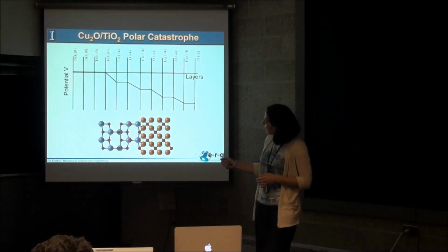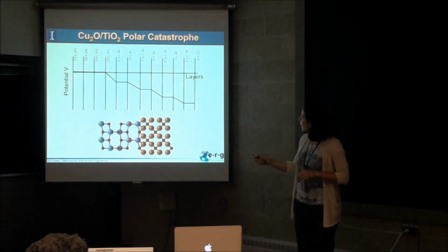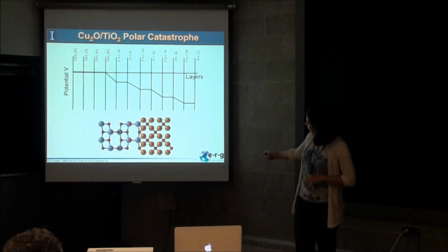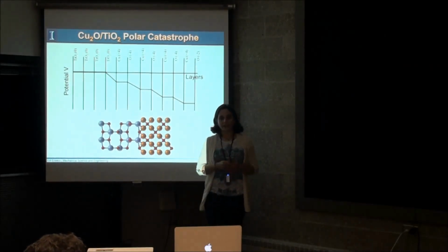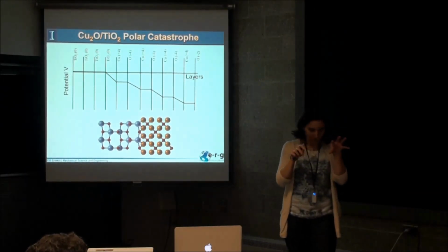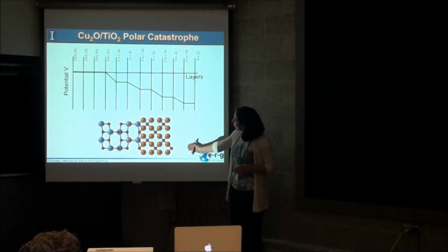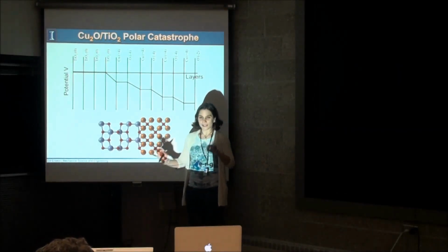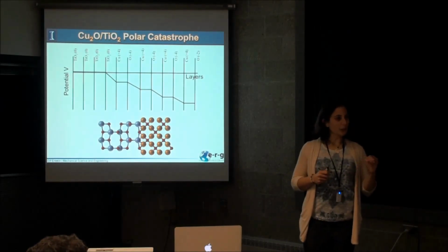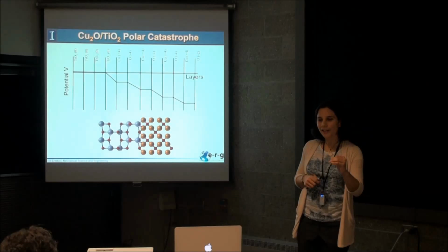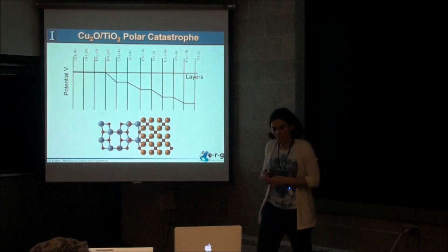But there's this unique world where we can intersect finite size effects together with polar interfaces. In finite size or nanoscale systems, this divergence of potential doesn't actually occur. And so there may be this neat playground where I can take a material that in its thermodynamic limit would be unstable, but through finite size effects, I could make it a little bit more stable. I could put it on the verge of an instability, or I could make it a really good water splitting system, potentially, because it's a material that is on the verge of an instability. And so that's the idea with this system here.